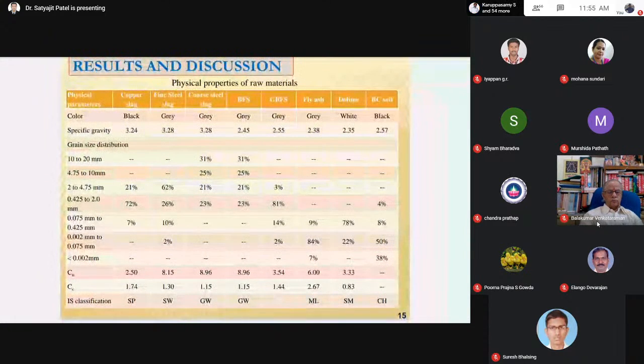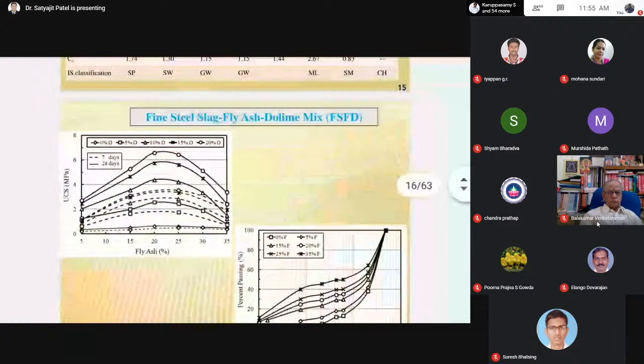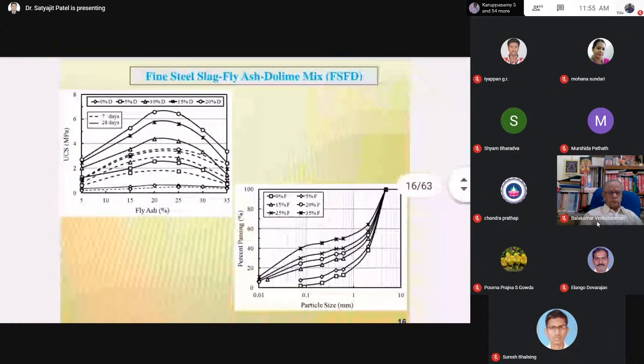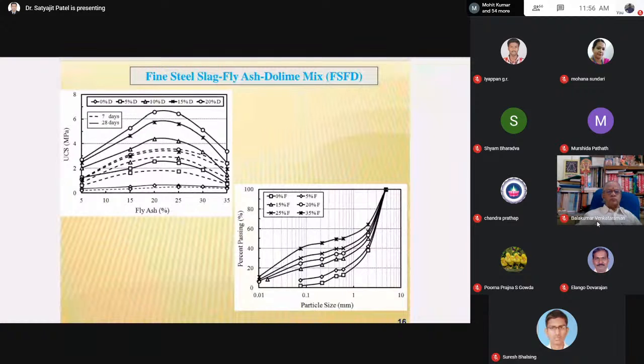That fly ash, dolime, black cotton soil, all these things. Then the fine steel slag, fly ash, dolime mix. So these are the test results from the UCS, that is unconfined compressive strength test. For different fly ash percentage and different dolime content, for 7 days curing, 28 days curing, the UCS value initially increases, then decreases. That indicates that at around 20 to 25% of fly ash content, it gives the well-graded sample and giving the maximum strength.